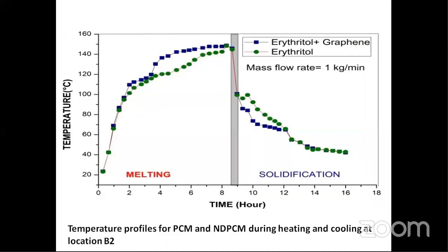One thermal cycle consists of one complete melting and one solidification for PCM and NDPCM. The melting time of NDPCM was reduced by 22% as compared with erythritol. The solidification time of NDPCM was decreased by 23% as compared with pure erythritol.